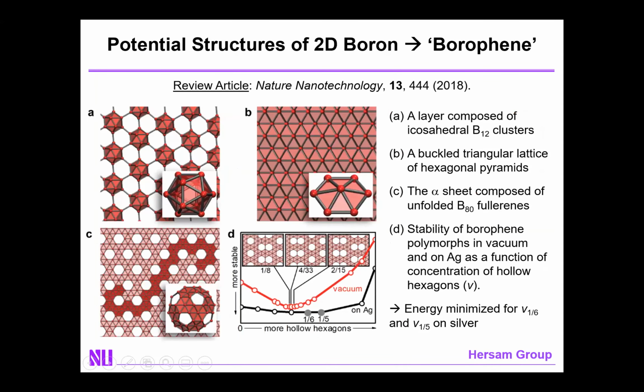And as a result, if we imagine going from the bottom up, there are several possible structures of 2D boron. You could imagine those icosahedral B12 clusters forming some sort of 2D lattice. You could imagine the buckled triangular lattice of hexagonal pyramids. You could also imagine taking a B80 fullerene, unrolling it, and then forming that into an extended 2D lattice. And that would be a triangular lattice with a periodic array of hollow hexagons or vacancy structures.